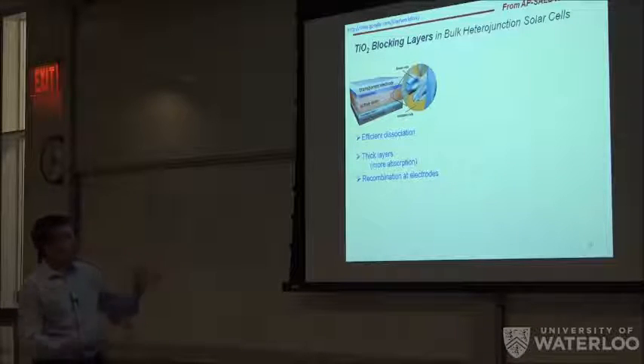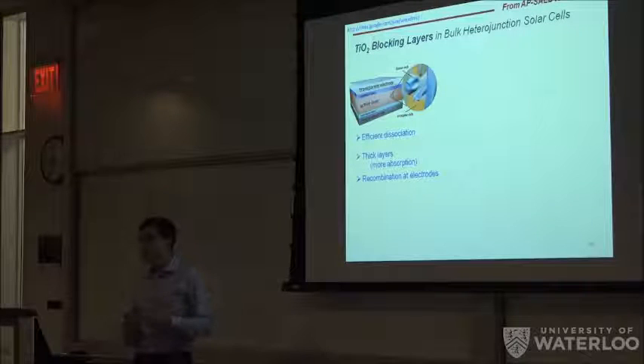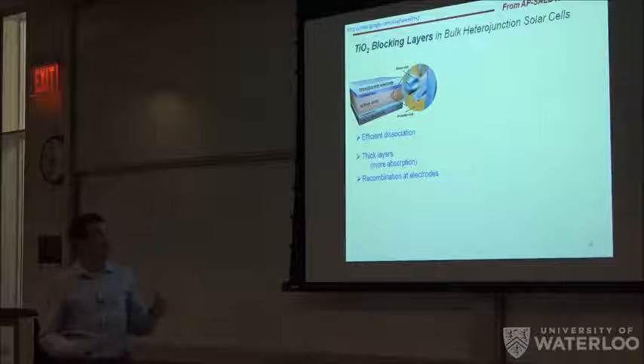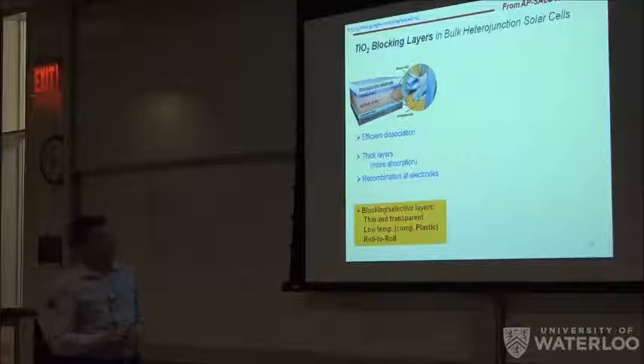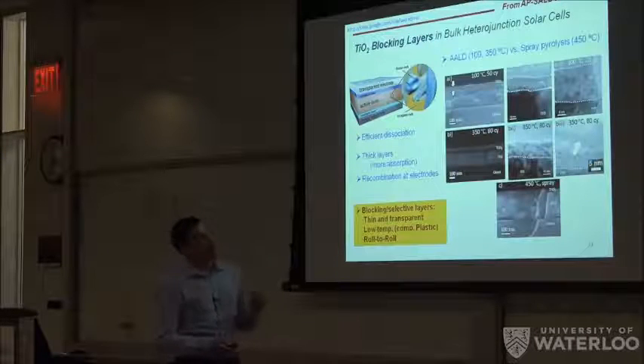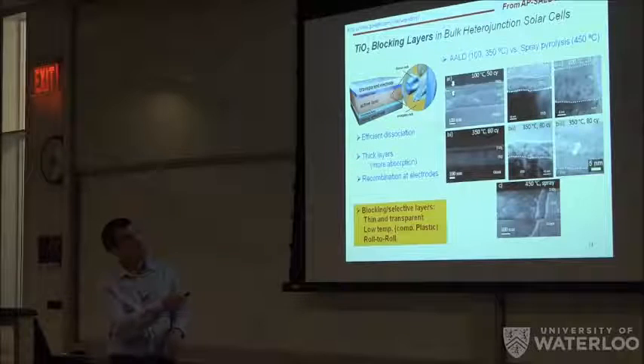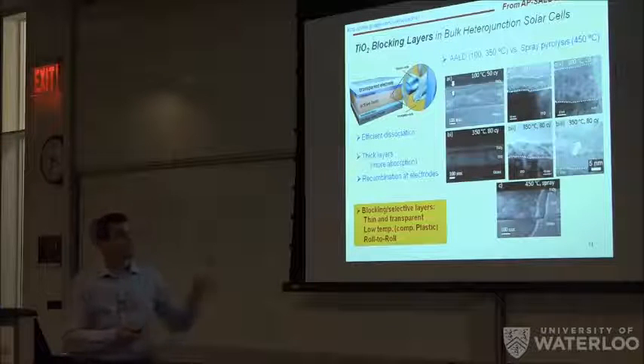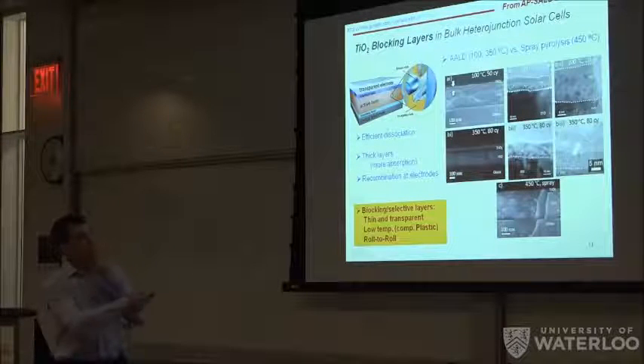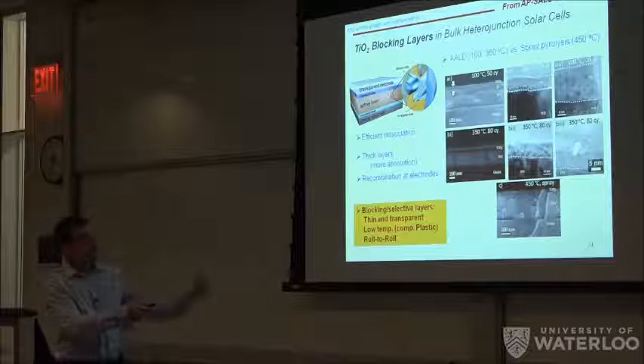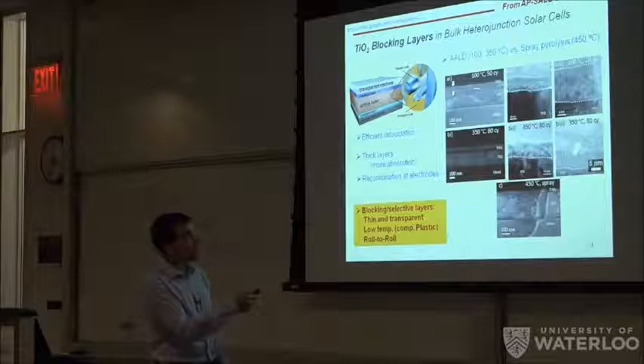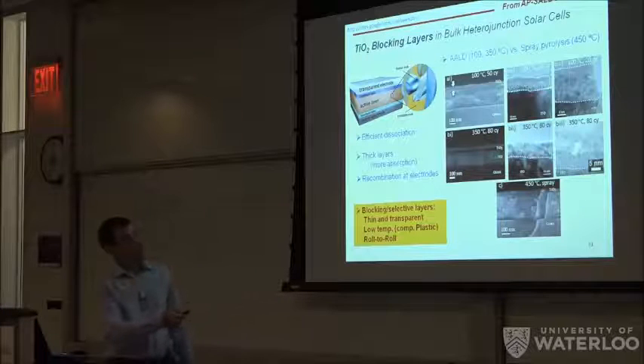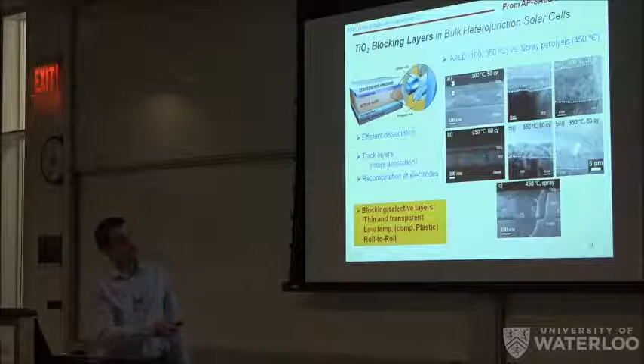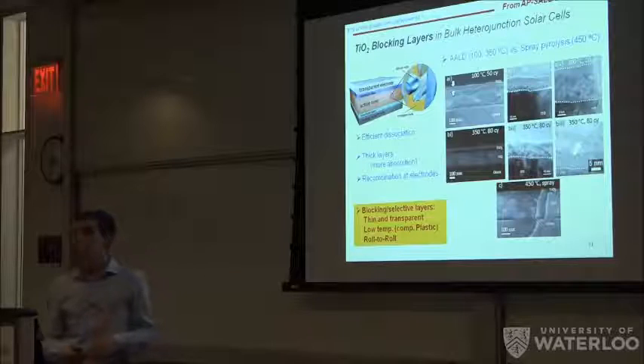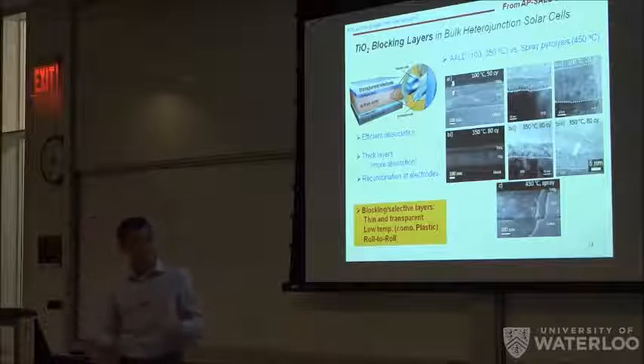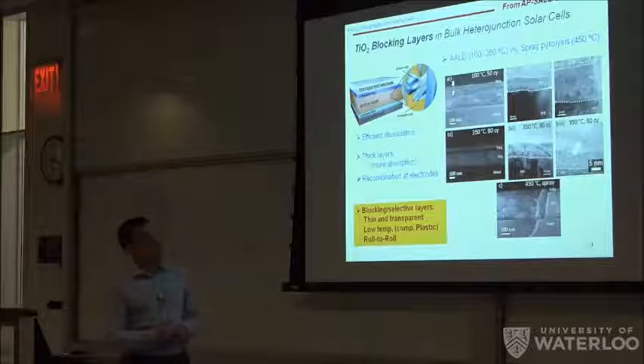And we do that by depositing oxide layers that should be, of course, compact, homogeneous, as thin as possible, and transparent. So we decided to apply a TiO2 layer on this type of cell, and the A here stands for atmospheric ALD because at the time we still called it like that. And we deposited a very thin layer of TiO2 on top of this bulk heterojunction. We did another one at 350, this was at 100, and then we compared with a layer made by spray pyrolysis at 450, which we knew was good, compact, and would perform nicely.